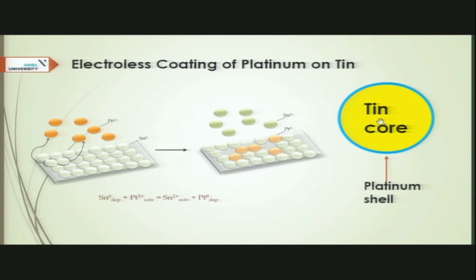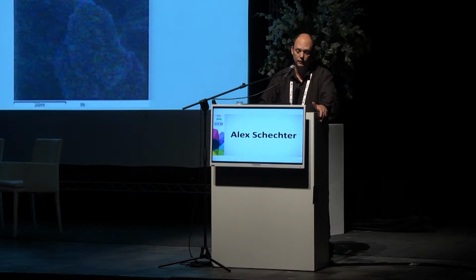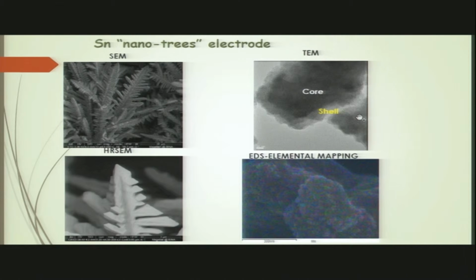Now, another approach regarding catalyst support, we're taking a core shell approach that's similar to what Professor Pellet presented before. We're taking tin and we're doing what's called electroless coating. That is, we're using the spontaneous reaction between platinum and tin to coat a very fine layer of platinum and save the huge amount of platinum that should have gone to the core. Here you can see a very nice structure of tin that we have developed. We call it nanotrees. And here you see the core of tin surrounded by 4 nanometers of platinum, evenly dispersed on the catalyst.